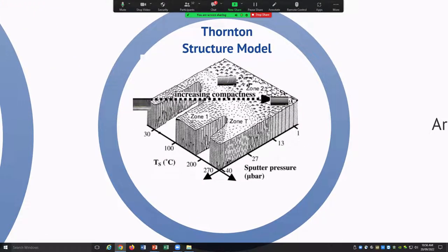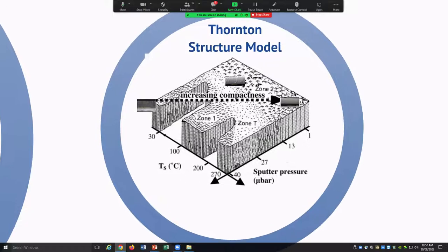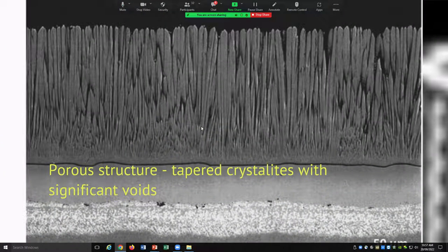So why is the arrival energy of the particles so important? We go back to a little bit of literature. Thornton came up with his structure model, and in this case it's looking at the temperature of the substrate and the sputter pressure. Both are analogues for the actual energy of the system. As you put more temperature in, you get more energy. As you reduce the pressure, mean free path goes longer, particles arrive with more energy. So we get to go from high pressure, low temperature. Your coatings can look like this. They're porous, with columnar sort of structures in there.